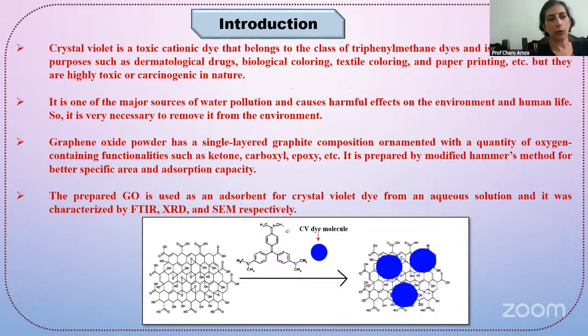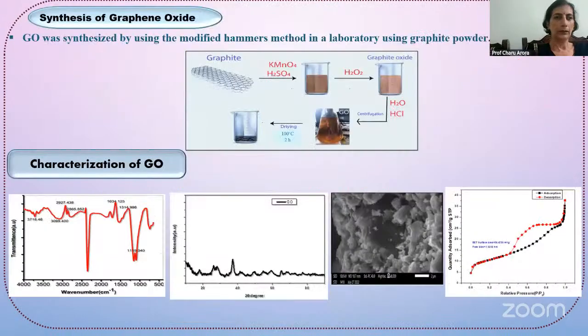Graphene oxide, we have already discussed, is a layered structure, and when it comes in contact with the crystal violet dye molecule, the dye molecule gets adsorbed on the graphene oxide. It was synthesized using the modified Hummers' method and characterized by FTIR, XRD, and SEM. This slide is showing the synthetic methodology and characterization.